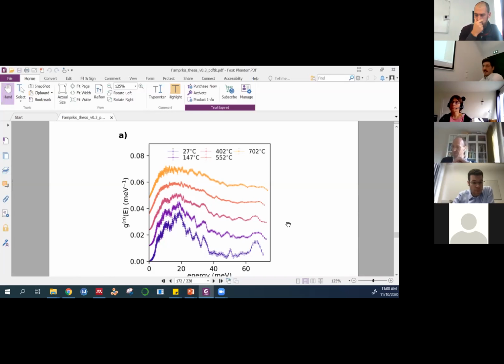Well, basically, again, there are a lot of effects that can come into play, and you described two of the main ones, right? For the rearrangement of the structure, you are going to need a certain diffusivity, let's say, of each component. You might also need to break and create bonds, so the energetics and the kinetics of that, and then the mobility of the species, because typically such interfacial reactions that we're discussing have to do with separating a phase into a lithium-rich or sodium-rich and a lithium-poor part under the effect of the applied current. But beyond that, I'm not sure exactly what your objection or your confusion is. What is the contrast?